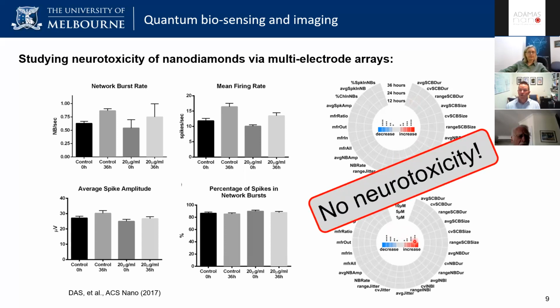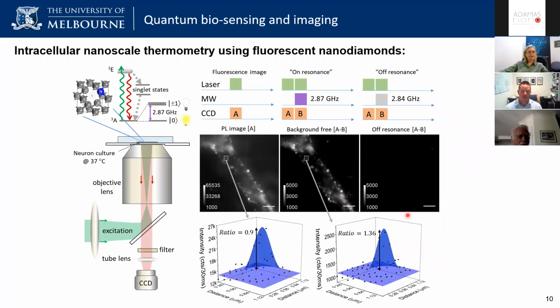So we were able to show from this study that these fluorescent nanodiamonds, and these were just bare fluorescent nanodiamonds, so carboxylated nanodiamonds, did not produce any neurotoxicity, which is a fantastic result. So if we want to use these sensors going forward in these sorts of systems, they appear to be biocompatible and do not exhibit any neurotoxicity, which is great. So then came the second part of the study, which was to ask the question of, can we do wide field imaging to start to report the temperature of these nanodiamonds inside the neuronal networks?